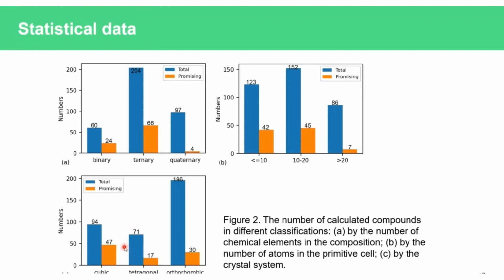Moreover, half of the promising candidates have cubic symmetry, 47 cubic versus 17 tetragonal and 30 orthorhombic structures, although the proportion of cubic compounds among all compounds is much smaller.